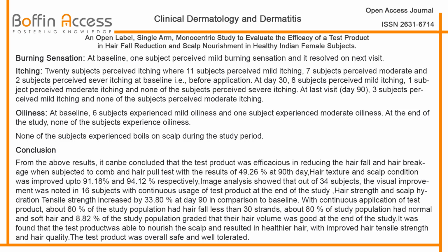Hair strength and scalp hydration: tensile strength increased by 33.80% at day 90 in comparison to baseline. With continuous application of the test product, about 60% of the study population had hair fall less than 30 strands, about 80% of the study population had normal and soft hair and 8.82% of the study population graded that their hair volume was good at the end of the study. It was found that the test product was able to nourish the scalp and resulted in healthier hair, with improved hair tensile strength and hair quality. The test product was overall safe and well tolerated.